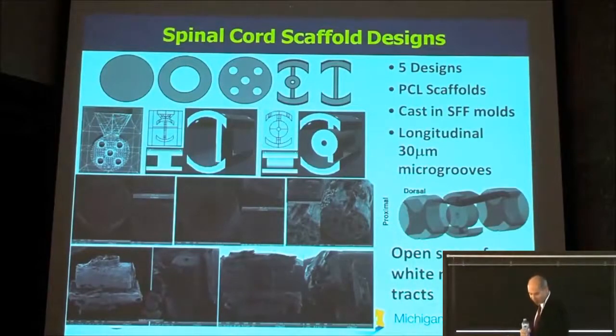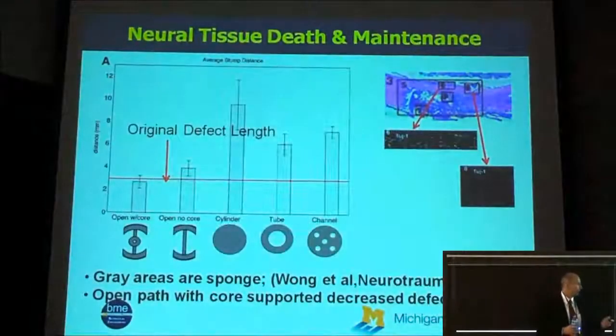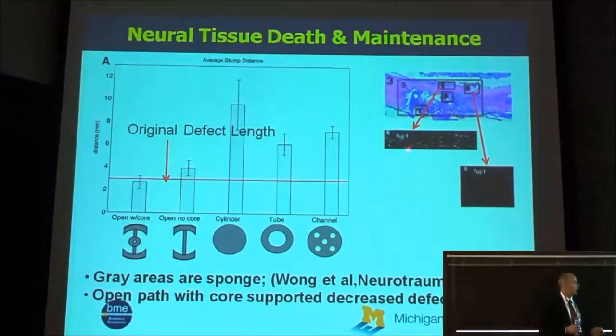We didn't put any factors in the defect, any neurotrophic factors or anything. And what we find, again, is that in terms of looking at Tuj1 staining as a measure of nerve growth, the actual design of the scaffold has an effect on nerve regeneration within the defect. In fact, for almost all the scaffolds except for this one, which was designed with open spaces in the white matter, the defect actually became larger over time in the spinal cord. So these are all small animal studies and in vitro studies that show that design of the scaffold has a significant effect. It's not going to grow tissue where none was there before, but the way that you design the scaffold does have a significant effect on how effective tissue engineering therapy is.